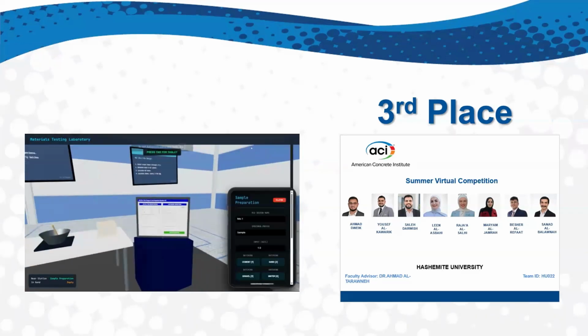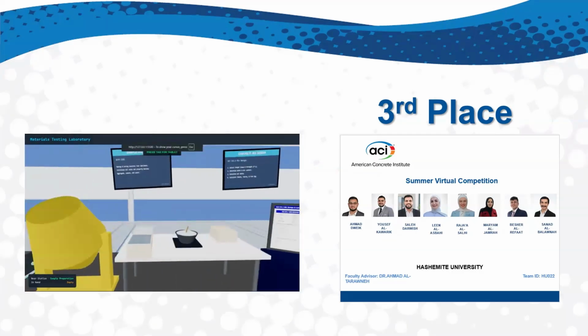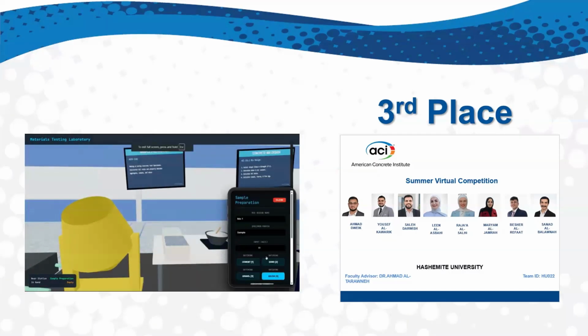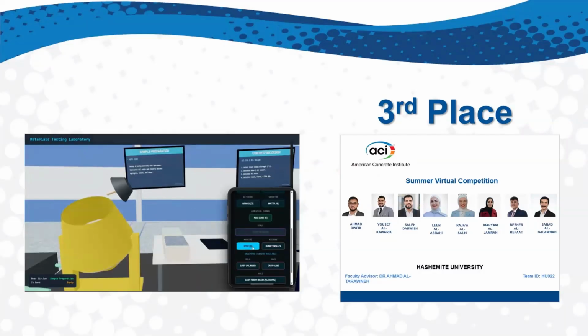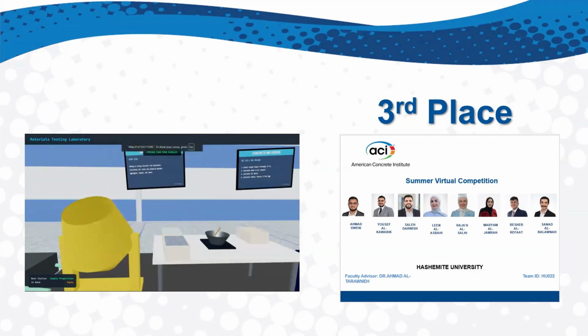Now, let's add the material to the mix, starting with water, 2 kilograms, 4 for cement, 7 for sand, and 11 for coarse aggregate. Now, after we're done with that, let's mix them. Put them in the mixer and run the mix. After that, let's dump it into the trolley. Now we have to cast. Firstly, let's cast one cylinder, then one cube.